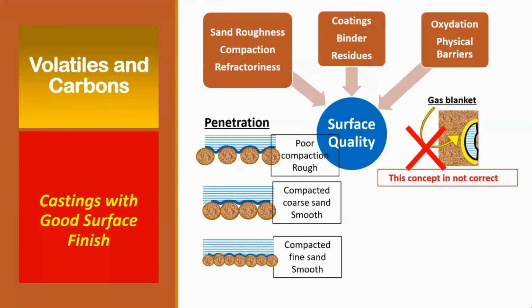So you will always see when you pour a heavier casting, the drag portion of the casting is rough compared to the cope portion. So this gas blanket theory doesn't work always, unless the metal quantity is very less, like exhaust manifold or small castings, where the metal itself is not much, and then there is a quick solidification taking place. In those cases, it might work.